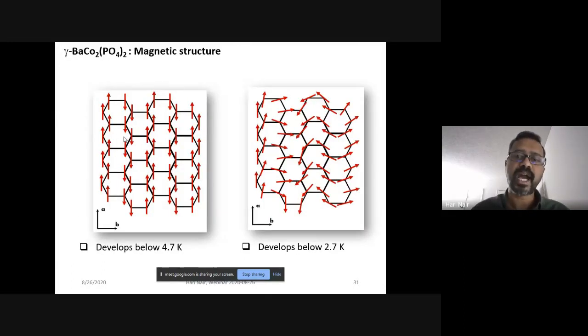So how would the magnetic structure, or the spin structure, look like? This is not the exact image. This is just a representation. This is just a cartoon. So the collinear order, where everything is in a line, collinear means everything is in a line. So you can see that all the spins point along a particular line. So you have a line of spins pointing up, then a line of spins pointing down, another one pointing up, likewise. This structure develops below 4.7 Kelvin.